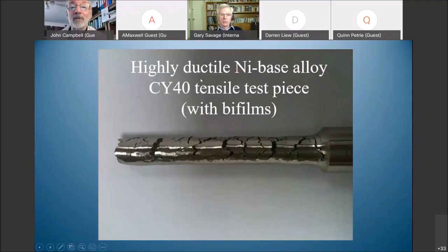This is back to our CY40 nickel base alloy, which we've cast beautifully badly, just cramming bifilms into it, because this is the world's most rotten running system I ever saw, and I played hell with the foundry and said they deserved what they got. They never did it as badly again, and now they can cast test bars that look beautiful and have decent elongations. Well, actually, this had a decent elongation, but not by plastic flow, but by opening of bifilm cracks. So you can just see it's just an unbelievable kind of situation in which the bifilms are totally in control of this overload fracture.